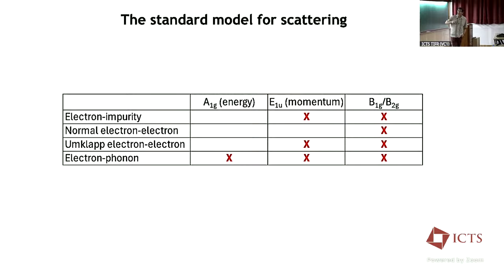Now, this is where we're going with this: through comparing these different channels, in particular watching how the different channels decay, we can isolate different kinds of scatterings. And so what I'm going to spend most of the time telling you about is the A1g channel, which is easy for us to see. We're still working on seeing this B1g channel, which is interesting for many reasons, but it's very fast decaying. There's no conservation law associated with it. At lowest order, it's neither a state of finite momentum nor a state of finite energy. It decays very quickly, and it's been very hard for us to see.